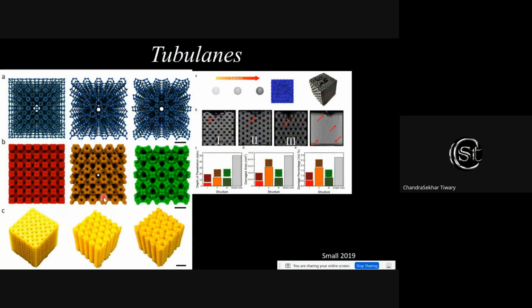And when I say complex topology, tubulanes are a carbon-based structure which was predicted in the 90s by several scientists, that if you take a carbon structure and modify the carbon geometry, you can make very complex nanostructures. When I say complex, I mean in the whole 3D structure, there is not a flat area you can find. Everywhere it's curved or bent. Now we take this computer generated structure, make it into a solid structure trying to retain the topology, and we put it into 3D printing.